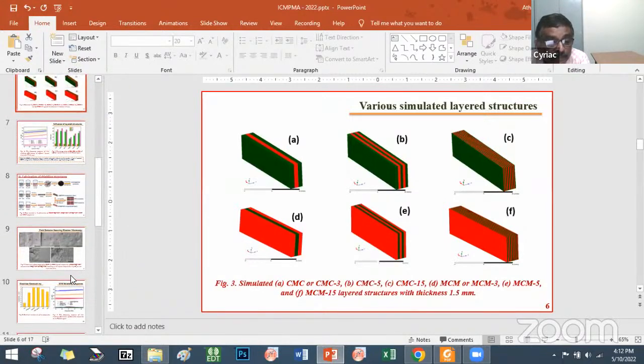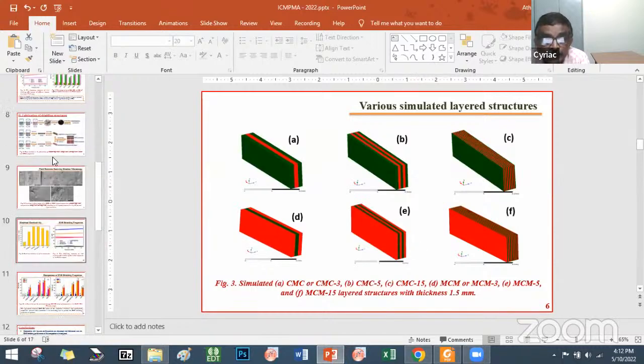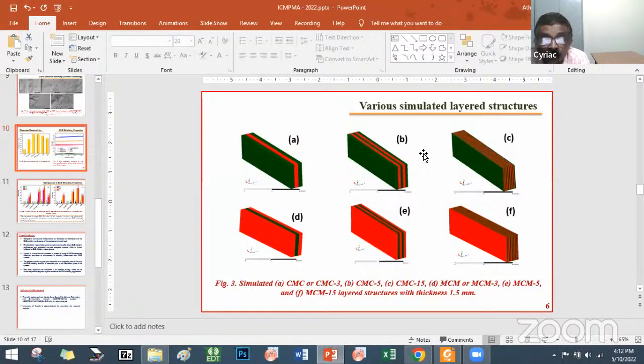because first of all, if we are using a magnetic material here, it will facilitate impedance matching. That is, the impedance of free space will match with the material, and the electromagnetic radiation will go in directly, rather than for a conducting material. It will get reflected a number of times inside the material, and eventually it will get absorbed, and very, very little radiation will come out. Around 99.9% of the radiation will get absorbed, as we can see from the measured value, which is around 60 and 40.